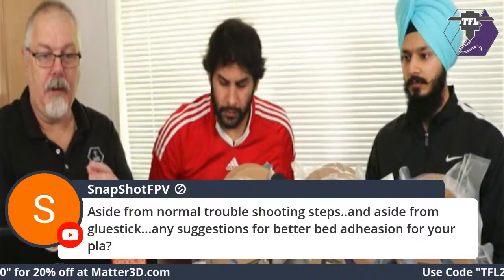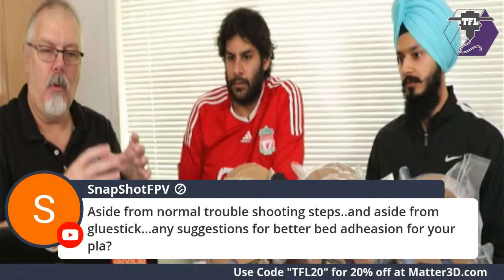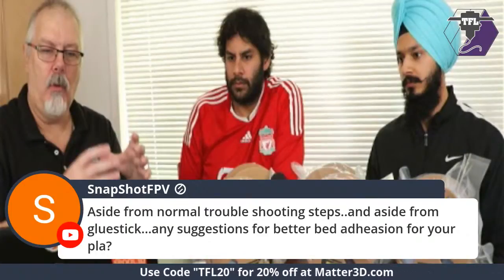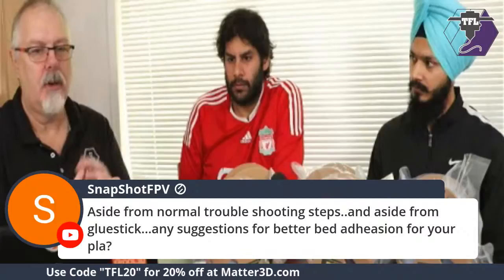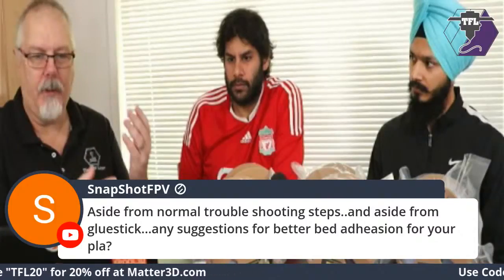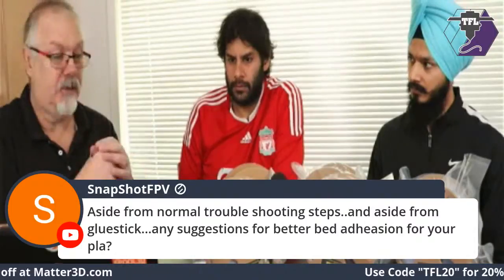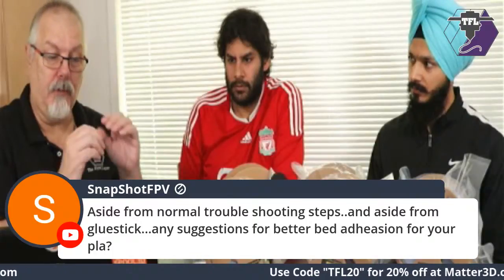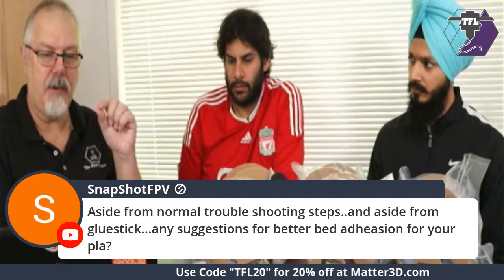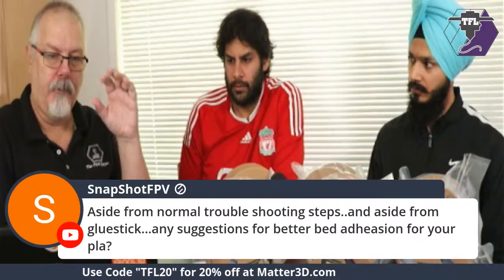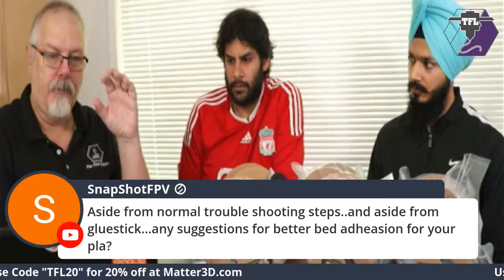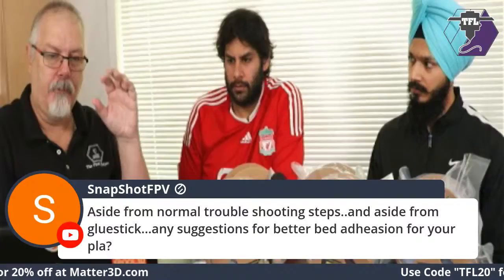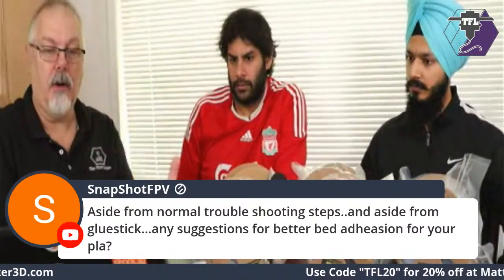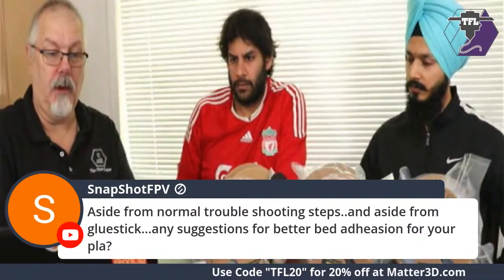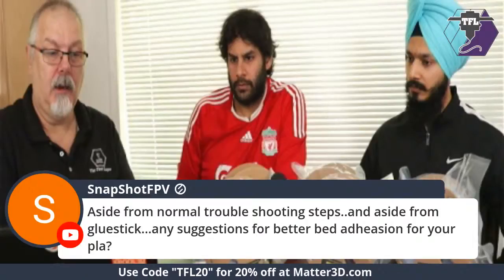Doesn't matter the material. That being said, with the beds that have the texture on them, you guys have all seen those. Creality has them. Everybody has them now. I find that the Matter 3D filament sticks to that, no problem. If you've got your offset from your nozzle to your bed set correctly, it's going to give you the best chance of adhesion, and you're going to end up with a fully fleshed out part at the end. And it's not going to curl on you.